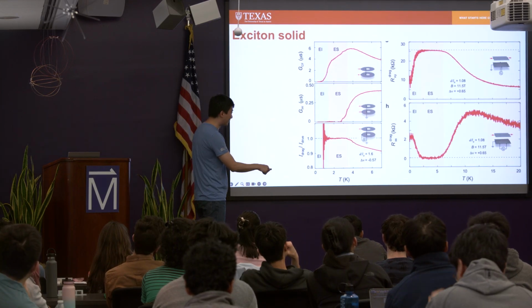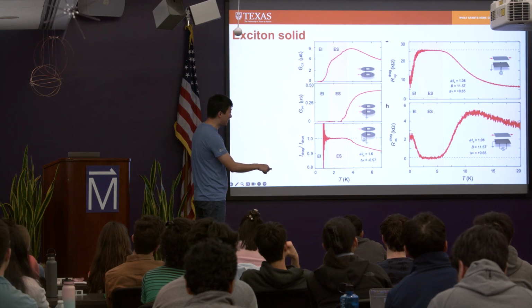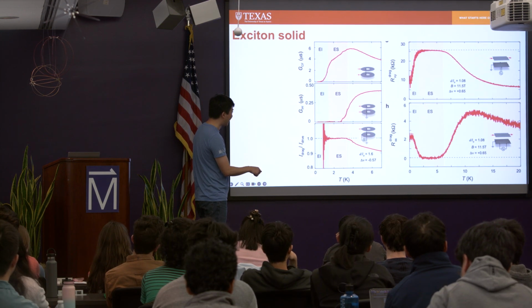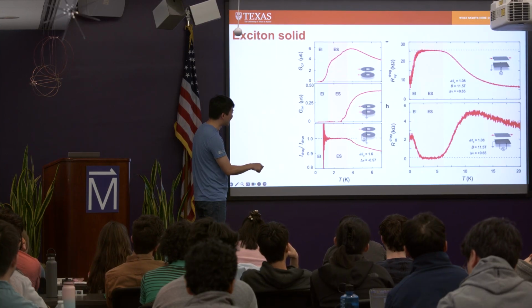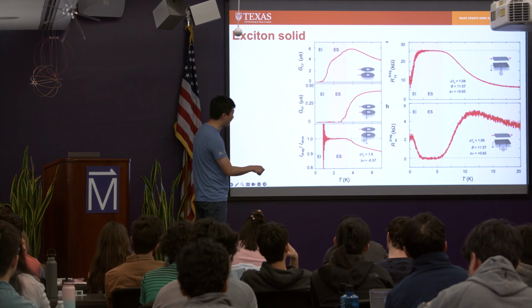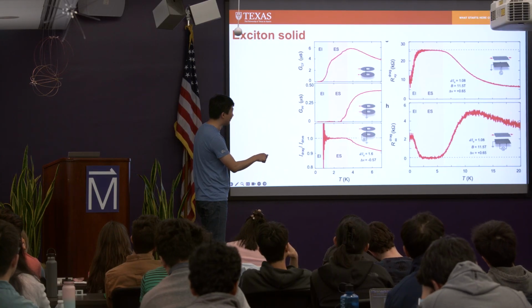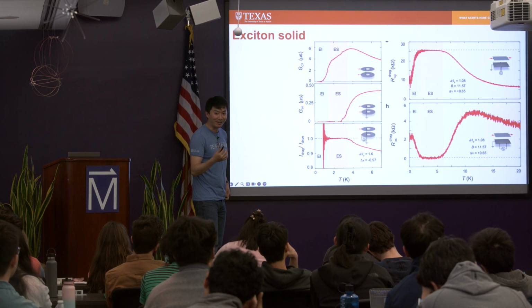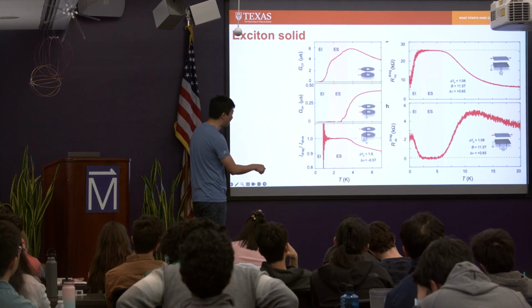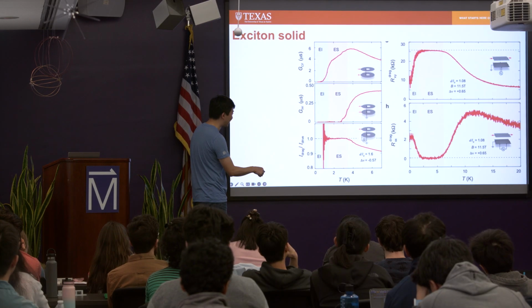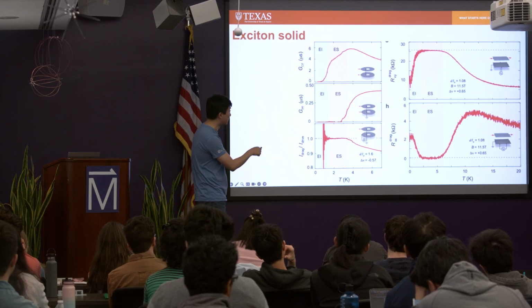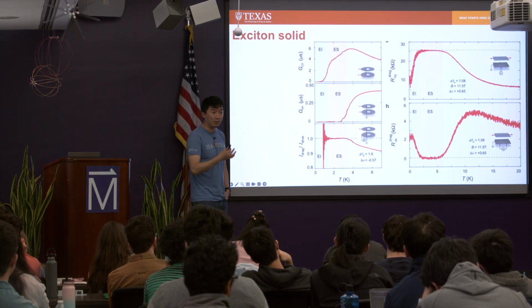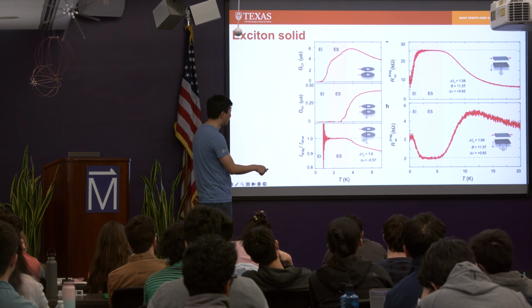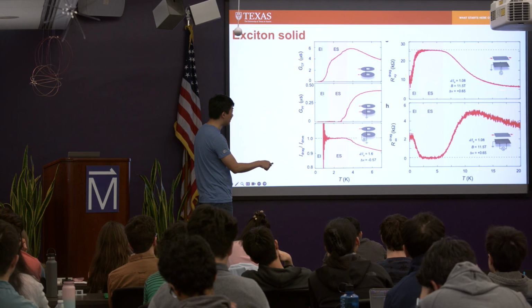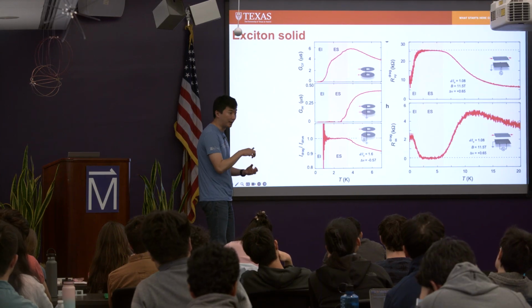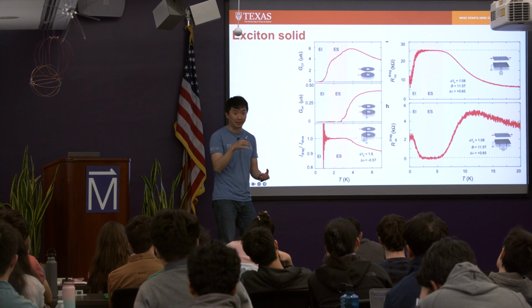right? It's almost the same condition also in the imbalanced state. And at low enough temperature, this is not an exciton condensate. It has finite resistance, and the Hall drag deviates from the expected plateau, right? But as you warm up around 1.5 Kelvin, it warms up into a state that shows zero longitudinal resistance and the quantized drag, meaning that indeed we warm up into a superfluid, right? And when you go up higher in temperature, then everything starts to deviate, right? The drag also deviates, meaning that now you're starting to depair the excitons, right?